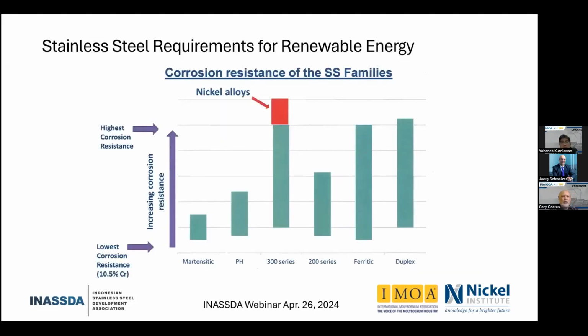And this I'd like to show just to show that the different families have a wide range of corrosion resistance. I could also show the same for the strength, but some of them, such as the martensitic and PH grades, they only have sort of the bottom end of the corrosion resistance, starting with the 10.5% chromium, which is the definition of a stainless steel, up to a somewhat moderate level. Whereas the 300 series runs from a fairly low level to a very high level. And as I mentioned, those nickel alloys continue on into even higher corrosion resistance. The ferritic and duplex alloys fall into that same range roughly as the 300 series, but they do have other limitations.